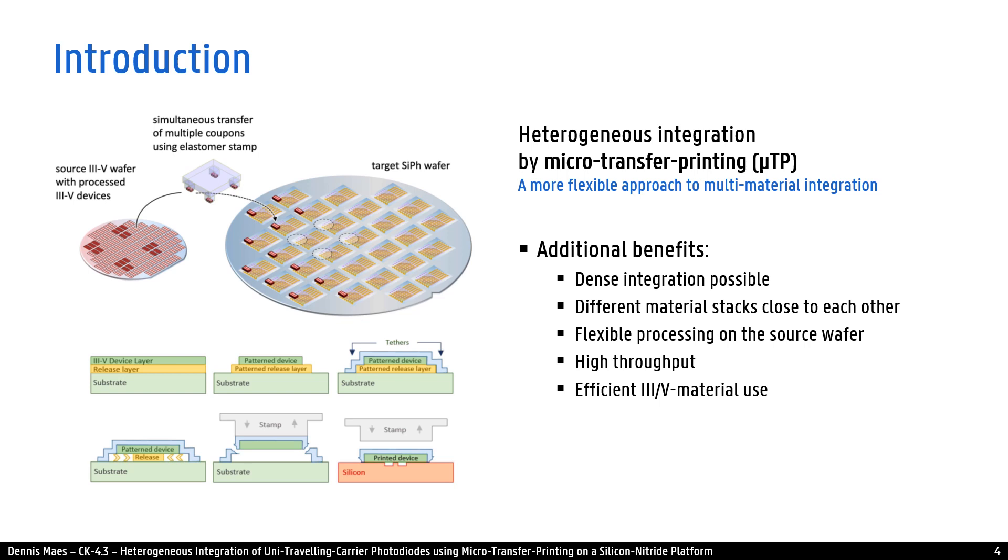It allows most processing to be done already on the source III-V wafer. This technology is scalable to production environments thanks to its high throughput, and it has a very efficient use of III-V material.